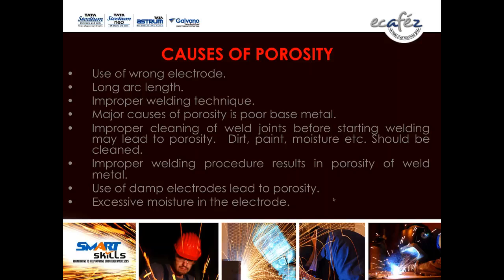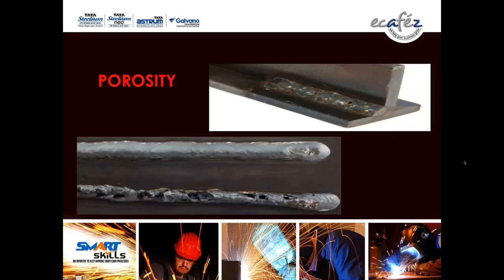Major cause of porosity is poor base metal. Improper cleaning of weld joints before starting welding may lead to porosity. Dirt, paint, moisture, etc. should be properly cleaned. Improper welding procedure results in porosity of weld metal. Use of damp electrodes leads to porosity. Excessive moisture in the electrodes. Check the pictorial view of porosity: in the above picture, this is a MIG process. This is also an MMA process.